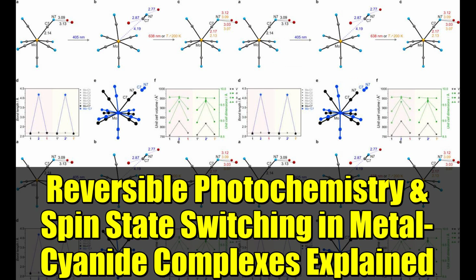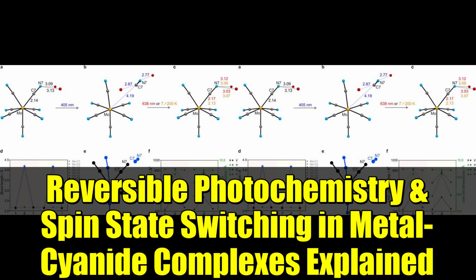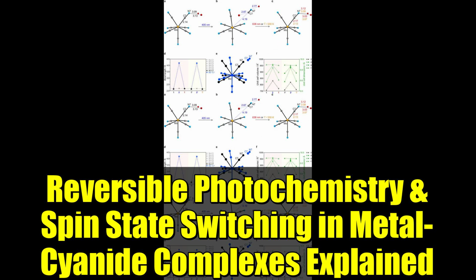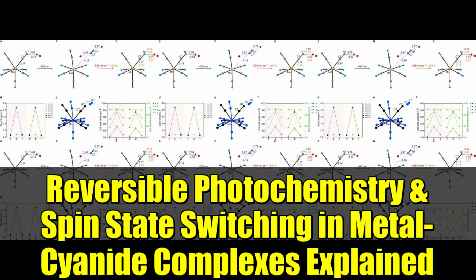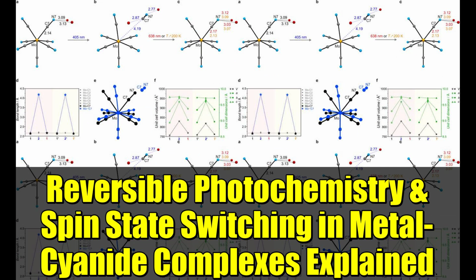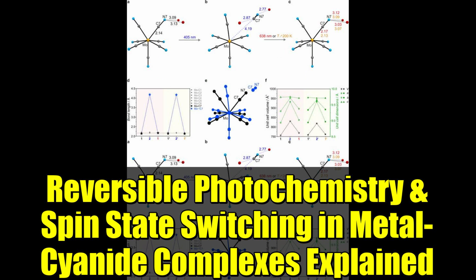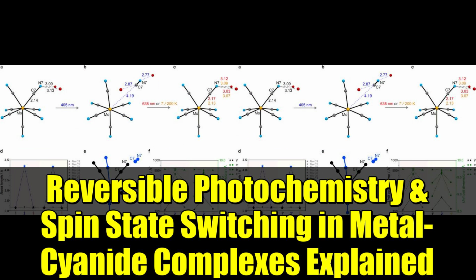Building on these insights, researchers have proposed a strategy towards high-temperature photomagnetic systems based on photochemistry, specifically the photodissociation of cyanometalates. In this study, we demonstrate a fully reversible metal-cyanide photodissociation occurring in single crystals of potassium heptacyanomolybdate dihydrate, K4Mo(CN)7·2H2O, 1. The single crystals of 1 undergo a complete metal-cyanide bond photodissociation upon absorption of violet light, resulting